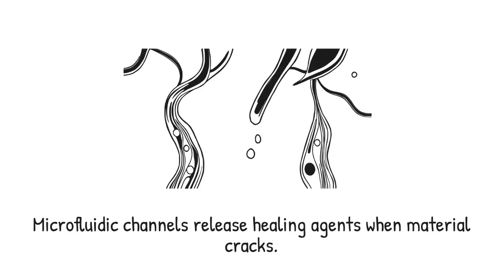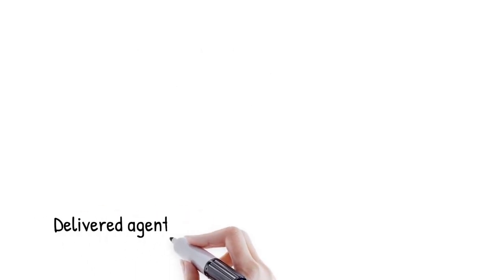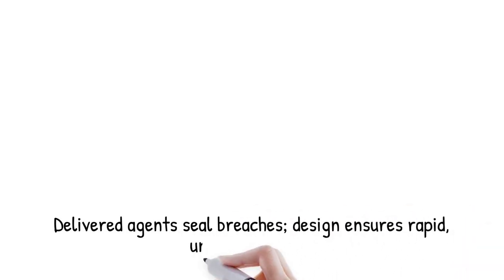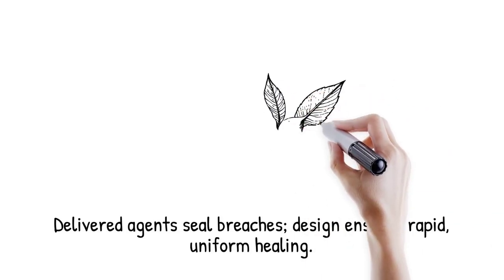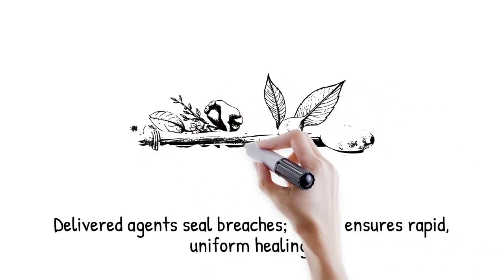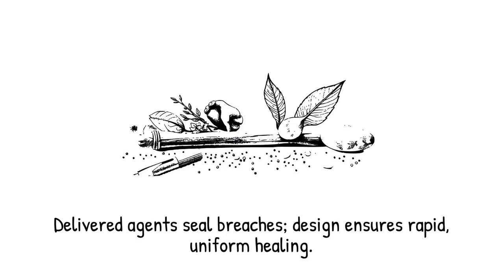When the material cracks, these channels rupture and release payloads into the damage zone. The released components polymerize or assemble to seal the breach, restoring functionality. Design of channel geometry and agent viscosity ensures rapid delivery and uniform distribution. Continuous networks can support multiple healing cycles by replenishing agents from reservoirs.